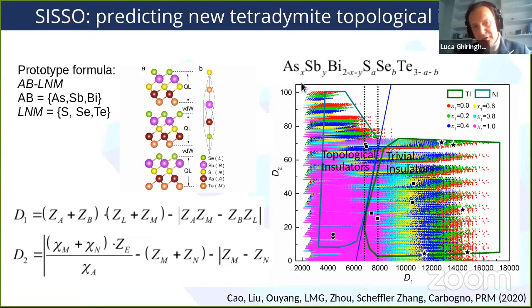Well, actually infinite, but we coarse grain or discretize x and y, a and b to some fixed points in order to have supercells of finite size. These are the points that were actually tried with DFT calculations, and they were always predicted correctly by our model. So now the challenge is up for the experimentalists to produce this material and see if indeed you can have all these new topological insulators out there.